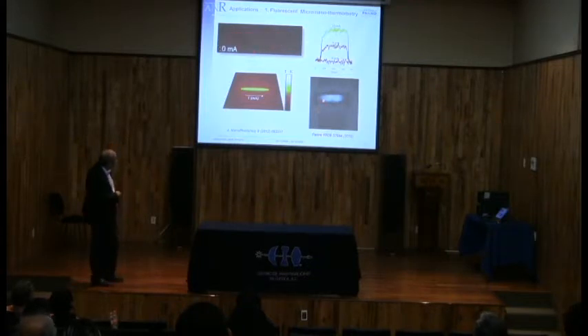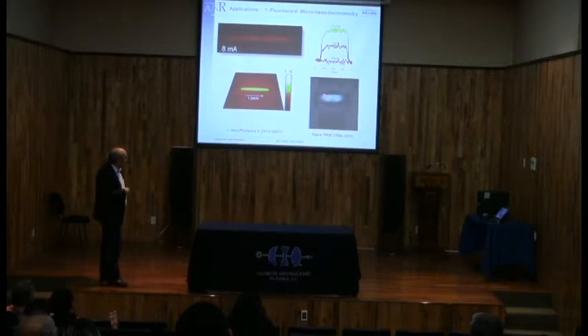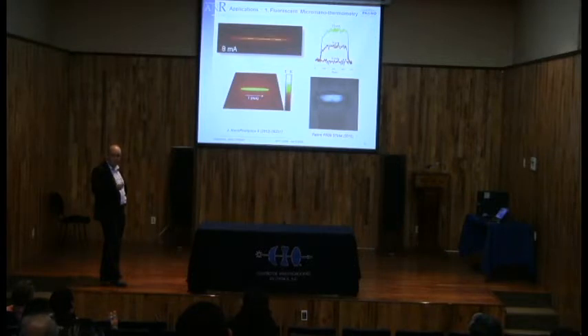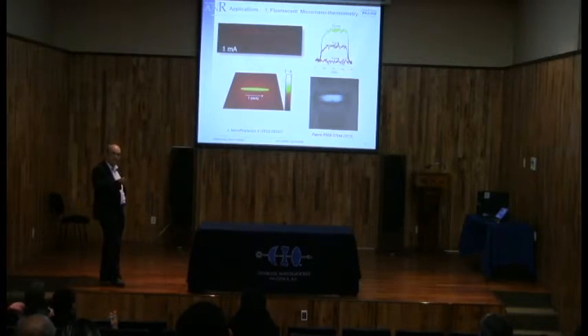But what you can see also here, we took several wires here and our film here. You see that spatially you can reveal the value of the temperature. That means that just by following the luminescence, you can, at the nanometric scale, follow the value of the temperature through the measure of the luminescence. And this has many applications in nanoelectronics or in electronic devices, and even in biology, where people need to know the value of the temperature with spatial resolution at the nanometric scale.